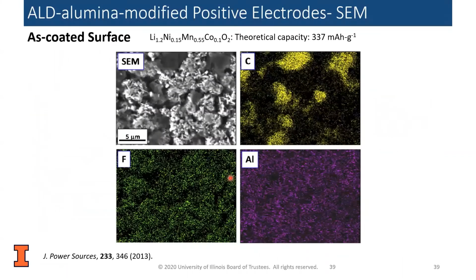And so here's some SEM and EDS images of the coated surface. We'll see here's what the surface looks like. You can see the binders kind of glowing like these little gumballs. Here's some carbon black. So you can see the carbon black in the carbon signal. And then you can see here that the alumina deposits pretty uniformly. And because the binder is pretty uniform throughout the layer, it was pretty uniformly coated as well.